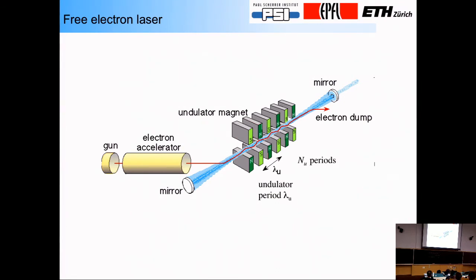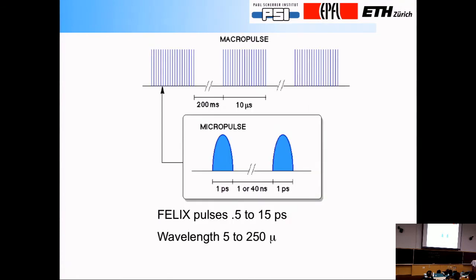And we had to actually develop free electron lasers, essentially to give us coherent pulses on demand to do exactly the same experiments that we were able to do with microwaves for the spins. Now, this free electron laser that we're using here happens to be in the Netherlands. It's now located at Nijmegen. It produces transform-limited pulses of radiation in the wavelength range 5 to 250 microns. That's exactly this terahertz domain that I was referring to before. And the pulses can be dialed in with lengths basically continuously between 0.5 and 15 picoseconds. So we can create essentially arbitrary length coherent pulses in this wavelength domain to now do optically what people had done with microwaves for spins.